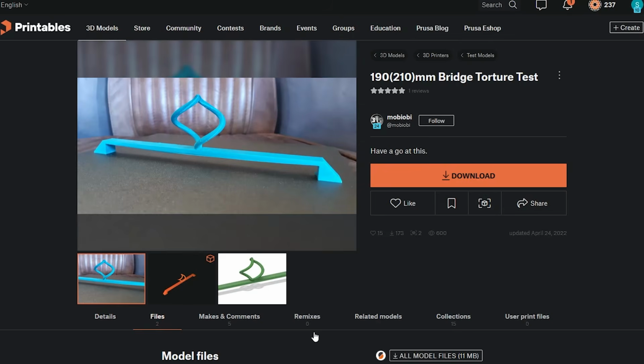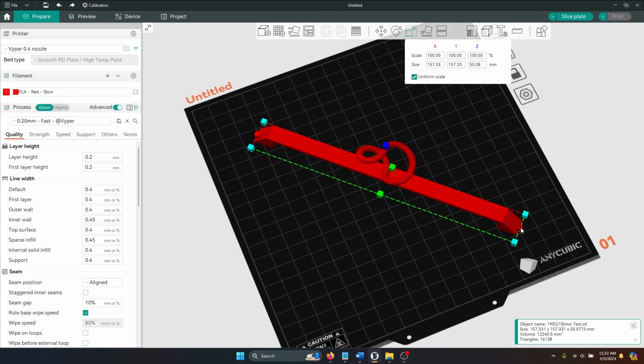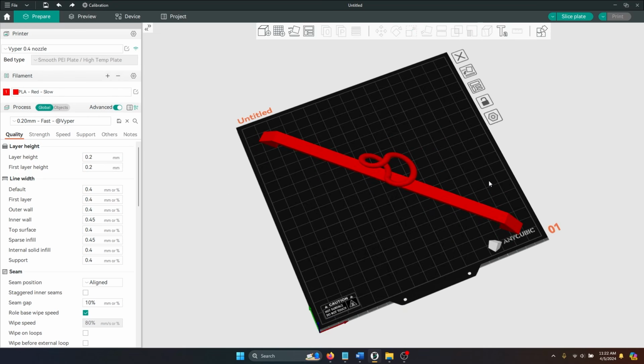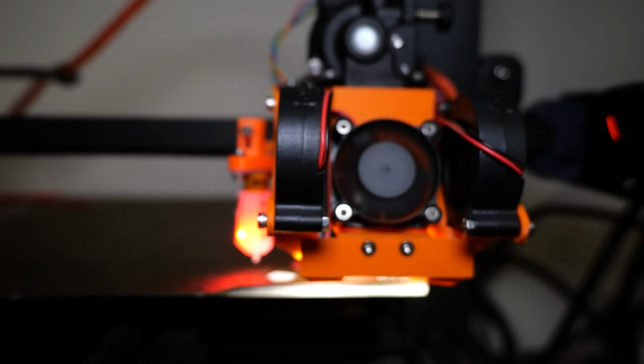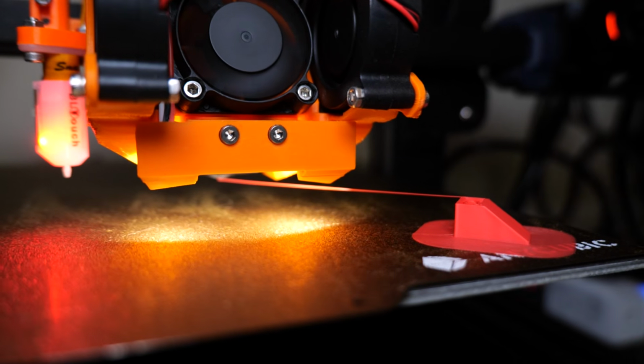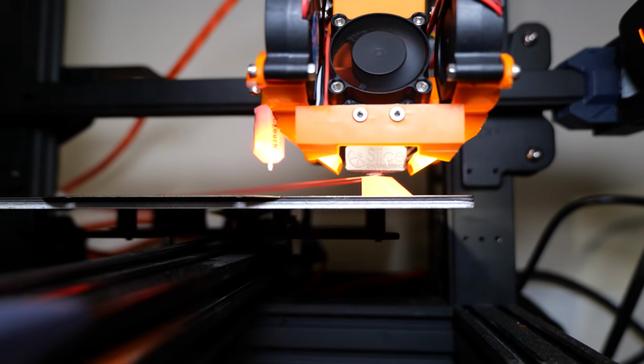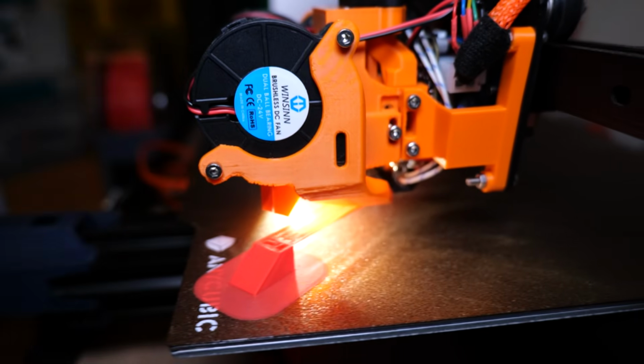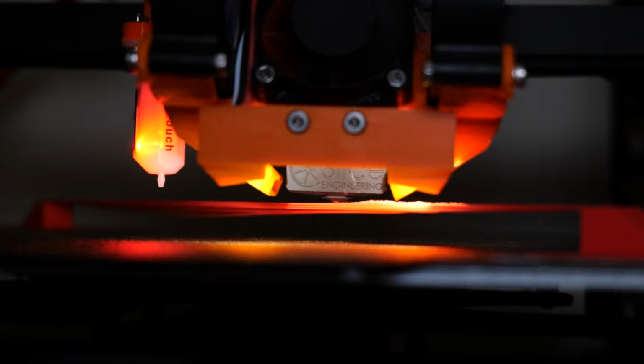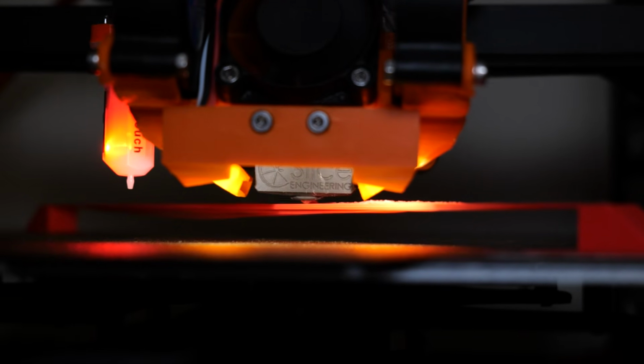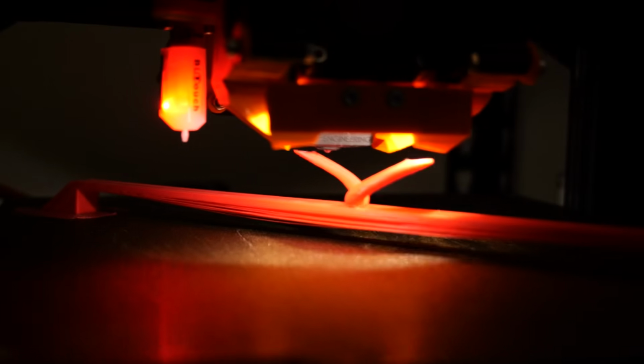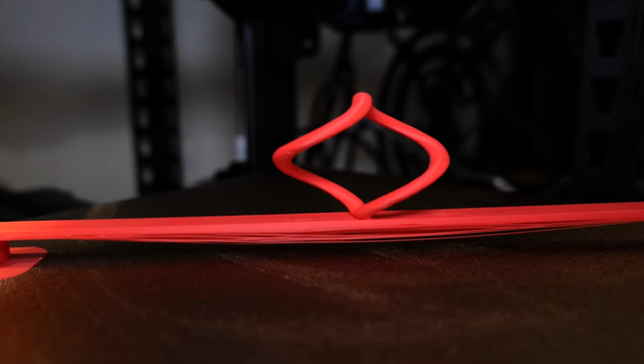The next thing I wanted to do was check out how the Hiromi did with some extreme bridging. I grabbed this really unique bridge off of Printables that has this cool overhang feature on top, so I imported it into my slicer and I stretched it out, which made the bridges longer and the overhangs even more steep. Check out how the Hiromi handled that. The bridging was pretty amazing at 200 millimeters or longer distances, without much sagging on that first layer that's deposited.